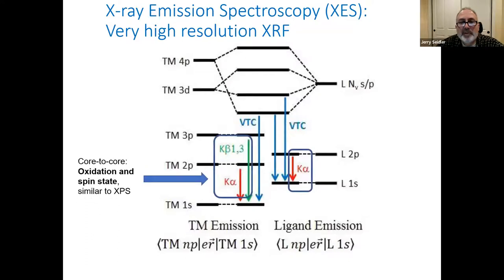And the core-to-core transitions are typically sensitive to oxidation and spin state and have a lot of similarity to XPS, but can have stronger multiplet effects and also tend to have smaller overall shifts in position of lines with changes in oxidation state. But besides the transitions that are purely intra-atomic, there are also transitions from these molecular orbitals, or more generally valence-derived states, down to core levels.